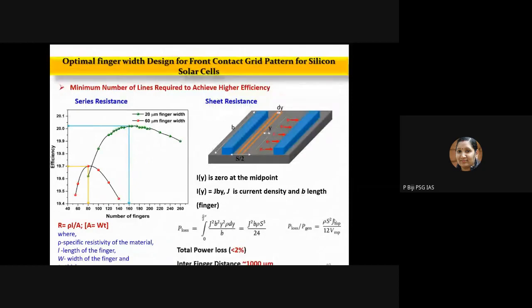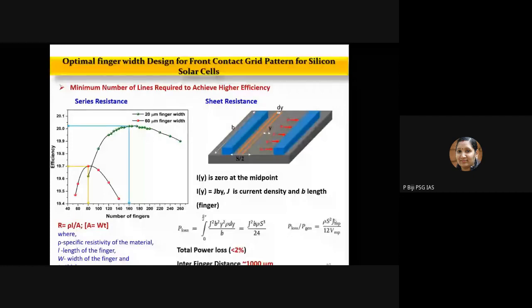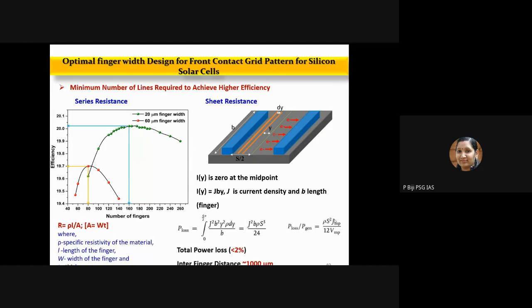Then further, we also checked the 20 micrometer finger width. We compared the efficiency to the commercial solar cell finger width, that is 60 micrometer finger width with 80 finger lines for commercial solar cells, whereas for our solar cell it was 20 micrometer finger width with 160 fingers. We could see a change in efficiency. Compared to the commercial solar cell, almost a 1% improvement in efficiency has been observed. Then we also calculated the sheet resistance based on simulations.